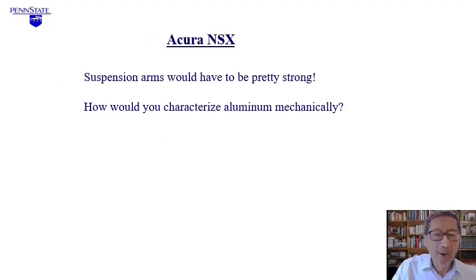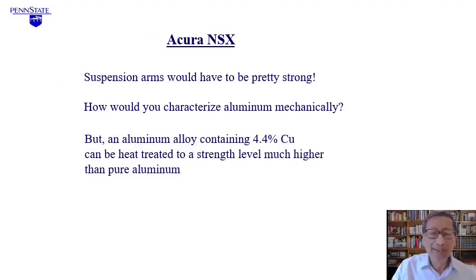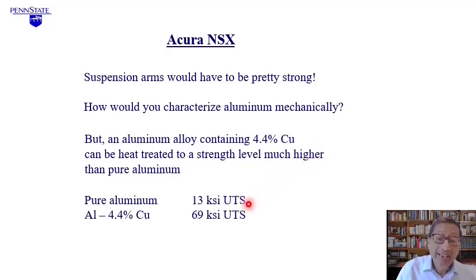Suspension arms have to be pretty strong, and aluminum we would call very soft. But if you add about 4.4% copper to aluminum and heat treat it, its strength can be dramatically increased. Okay, how much? 13 ksi for pure aluminum, and aluminum with 4.4% copper can give you 5 times that much. 69 ksi, unbelievable, right? And all of this huge change is because we added 4.4% copper. So look at the fantastic improvement in properties by adding a small amount of alloying element.